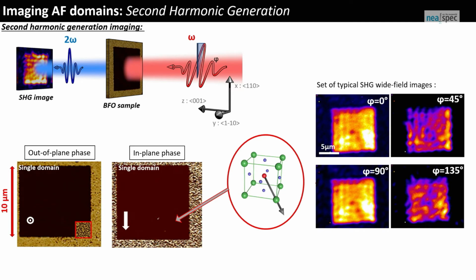What I have to mention is that our laser is a 1 kHz laser, 100 femtoseconds, and we have an OPA, and in this case the omega light wavelength was 900 nanometers. But then for different orientations of the polarization, you can definitely see the square, but for some other directions, you see substructures.